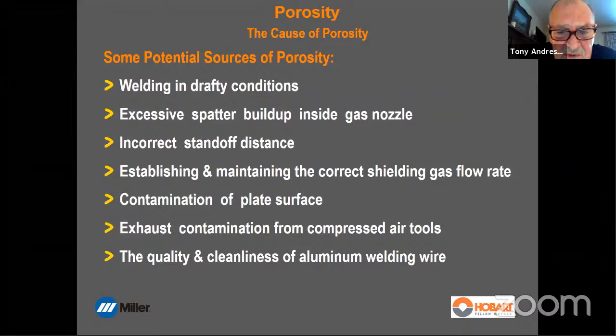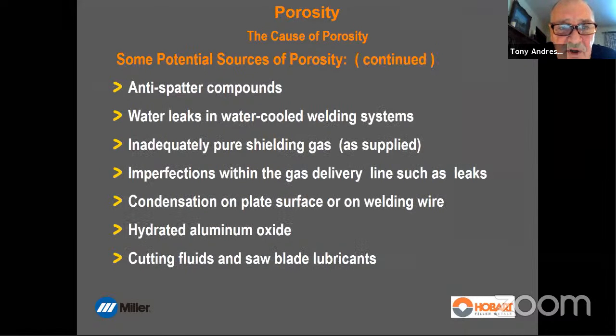You ain't going to get X-ray quality welds after you've subjected that weld wire to fluctuations in temperature and humidity and had condensation on the surface of it. You will have hydrated oxide and you will not get crystal clear welds when you X-ray them. Anti-spatter compounds, be careful. Not recommended for aluminum.